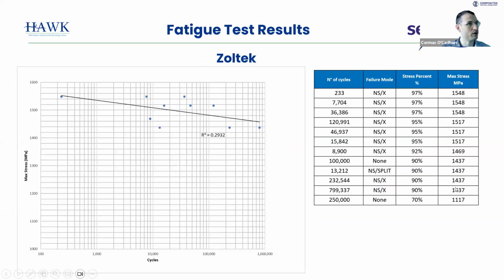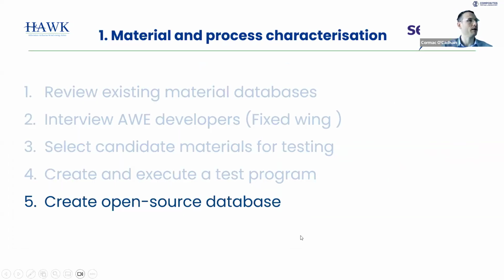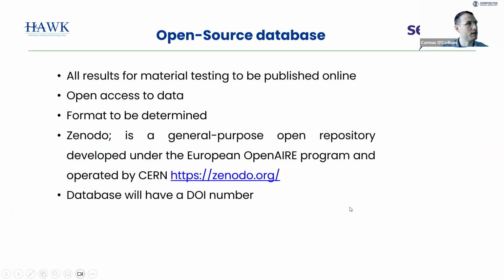And then we did the same for the Zoltek. We did fatigue, and we developed our SN curve here. We didn't have enough specimens to do any residual tests on that material, so we don't have that data. And then the last step was to create the open source database. So we're going to publish this online on zenodo.org, which is open access. And that'll really give developers a leg up when it comes to selecting these new materials.